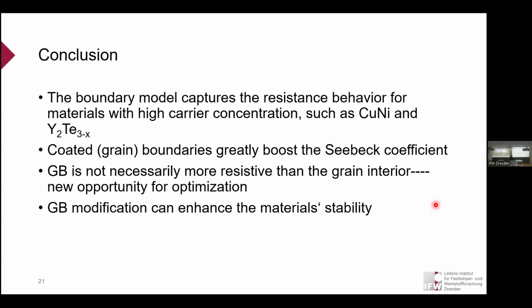The model is called energy filtering scattering, to effectively scatter the low energy charge carriers to promote the high energy charge carriers, and it applies pretty well for high carrier concentration materials such as metallic copper nickel, and degenerate semiconductors such as yttrium telluride.